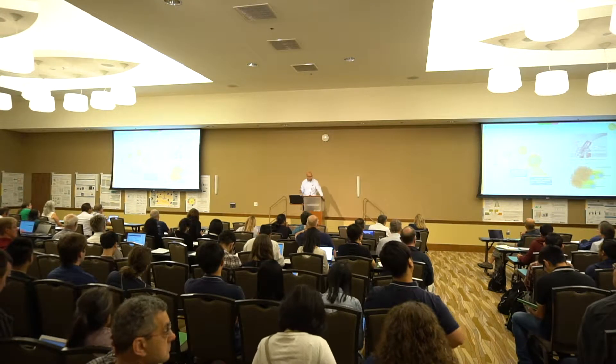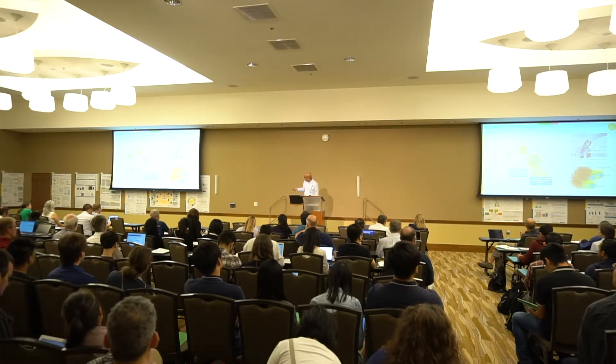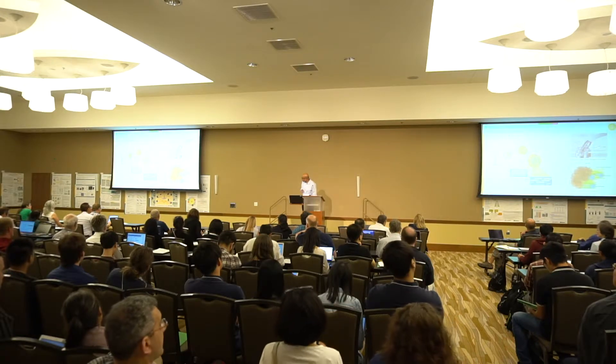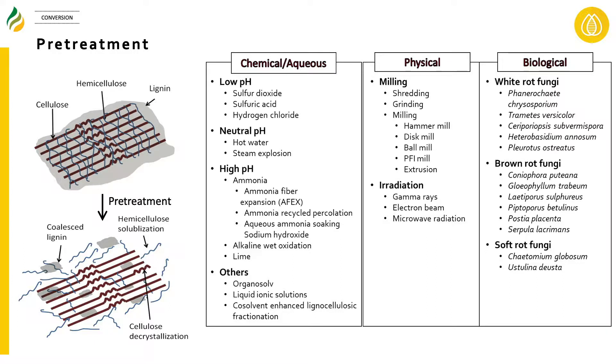In a model of the cell wall, the cellulose is represented by blue bars, surrounded by the green and yellow bars of hemicellulose. Brown is the lignin — the glue that holds the structure together and gives it recalcitrance. When we do pretreatment, we want to take apart that recalcitrant structure, open up and release the polymers of C5 and C6 sugars so that the enzymes can access them and convert them into monomeric sugars.